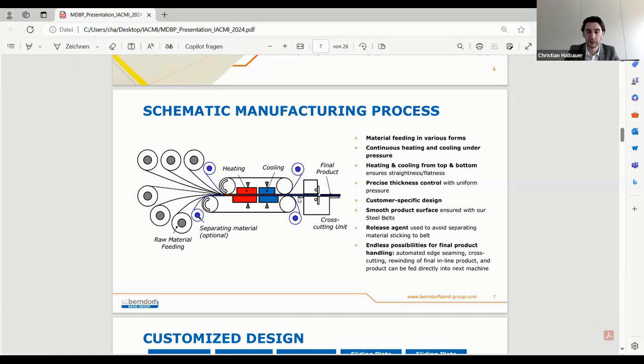And at the end, we usually apply a release agent so as to make sure that the product is not sticking to the belt. All of our release agents are PTFE and silicone free. So if you're engaging in any kind of automotive or aerospace industry, you'll probably be pretty happy about that, since this, at least as we know, is a very strong requirement there.